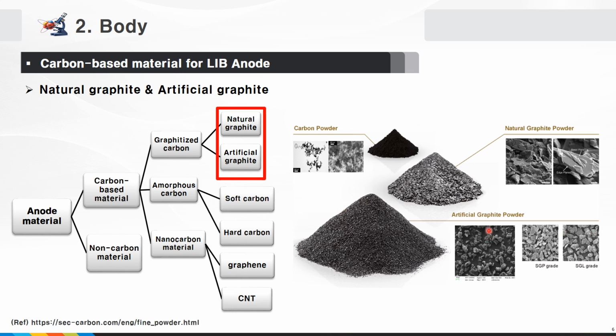Since artificial graphite applies high heat of 2500 degrees or more to form a crystal structure of graphite, it has a more stable crystal structure than natural graphite. So the change in the crystal structure is small and the life is relatively long. In general, artificial graphite-based anode active materials have a life 2 to 3 times longer than natural graphite, so it is possible to guarantee a 10-year life of a battery.